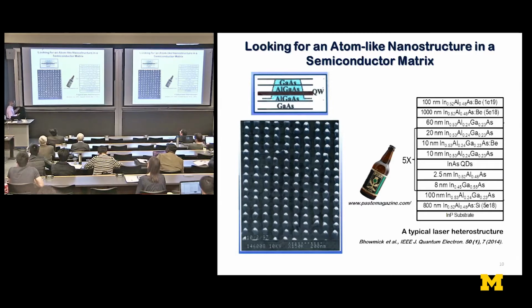And well, we did all kinds of experiments, spectroscopic experiments and characterization of the luminescence, time resolved, and all kinds. And you know, you get good papers out of these. But that's about it. I realized you could never make a laser out of this because, as you see, a laser heterostructure is pretty complicated. And you have to grow multiple layers. You have to grow layers below this, layers above that. There was no way you could do all that with this. So it was clear that with this kind of technology, you just couldn't have a practical device. Others still kept on trying, but I was convinced it couldn't be done.